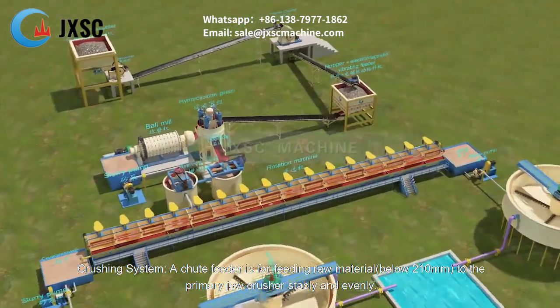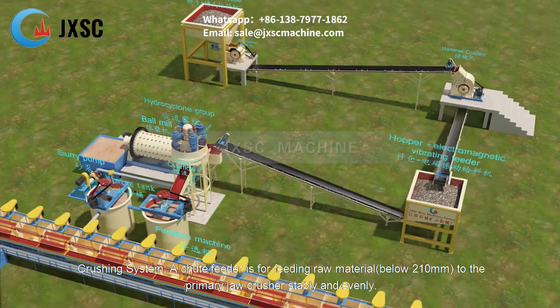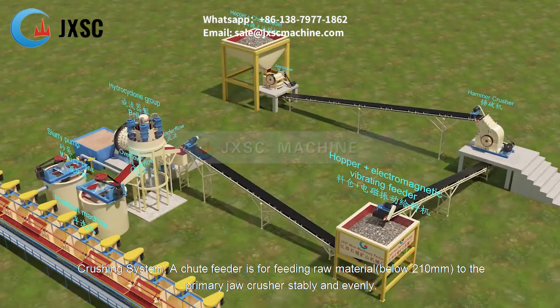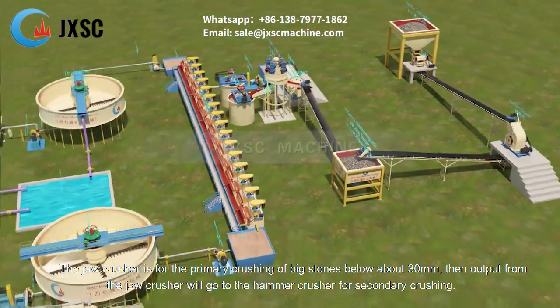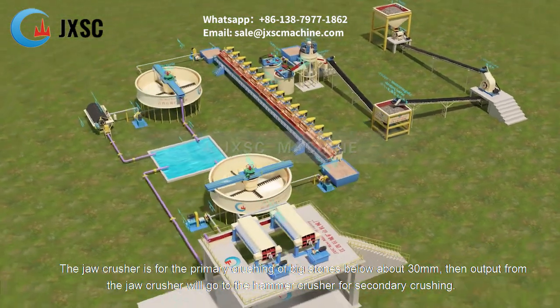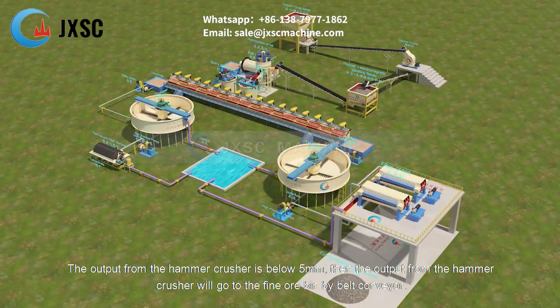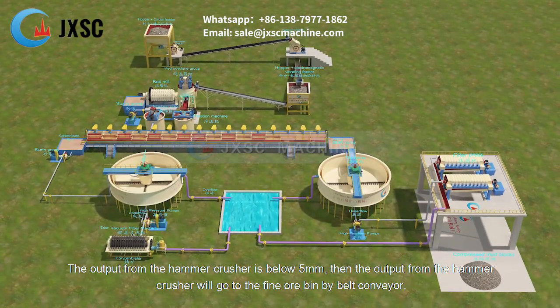Crushing system. A chute feeder is for feeding raw material, below 210 mm, to the primary jaw crusher stably and evenly. The jaw crusher is for the primary crushing of big stones to below about 30 mm. Then output from the jaw crusher will go to the hammer crusher for secondary crushing. The output from the hammer crusher is below 5 mm. Then the output from the hammer crusher will go to the fine ore bin by belt conveyor.